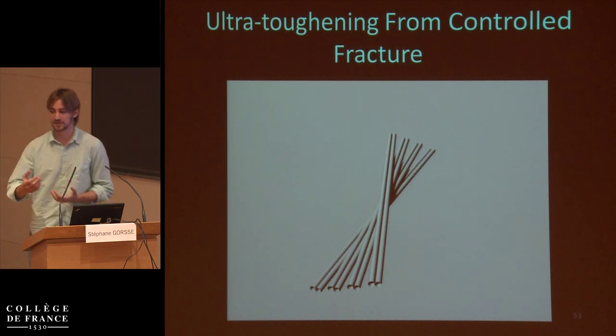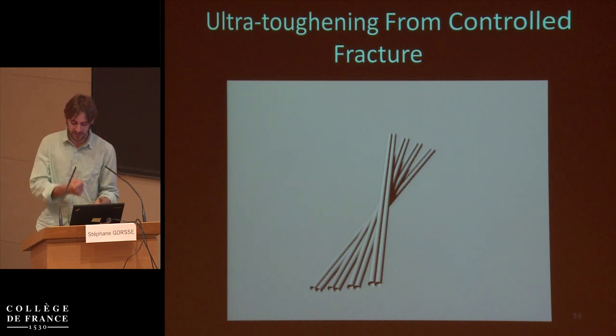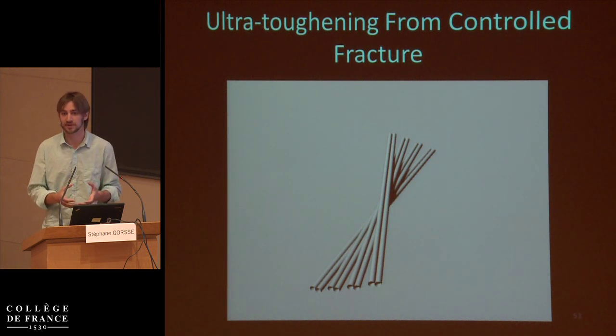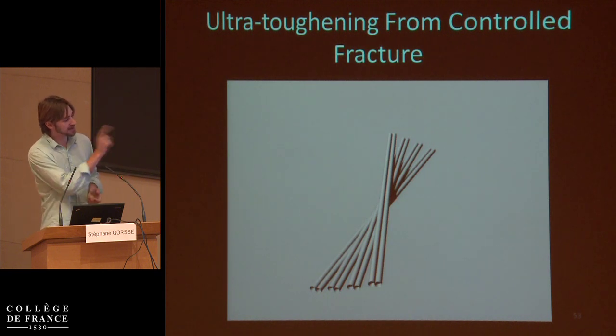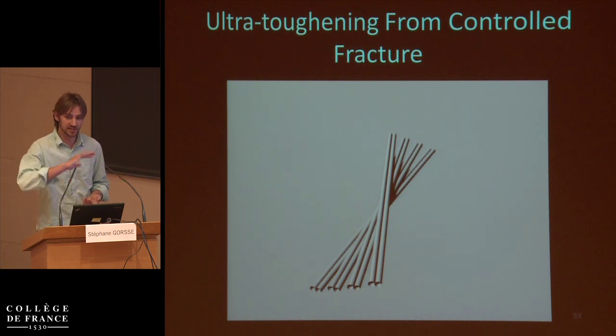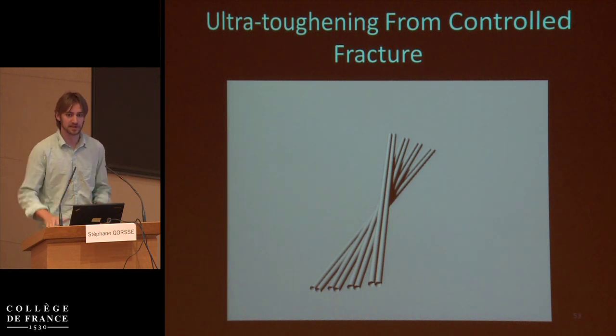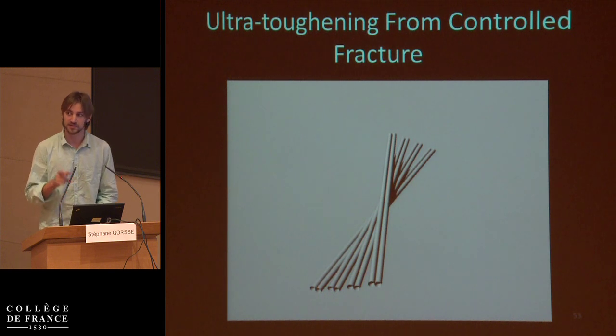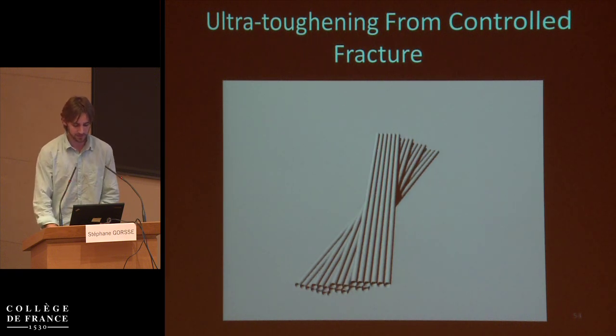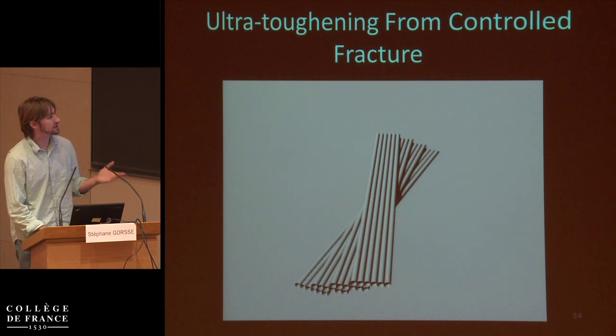And if we think about how this club is loaded, when you impact, the finite element model at least predicted that there's biaxial stresses forming laterally away from the point of impact. And that's sort of obvious if you just consider a Poisson's ratio. And so if it's a biaxial stress that's driving these fractures, as we rotate the angle, then that means the driving force is actually diminishing, to the point where it becomes easier to propagate a new fracture from a new seed instead of continuing the old fracture. And so instead of your fractures becoming unstable because you're increasing the crack opening angle, they become stabilized and then reinitiated.